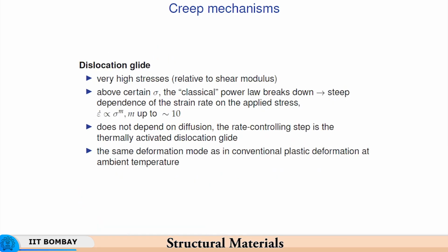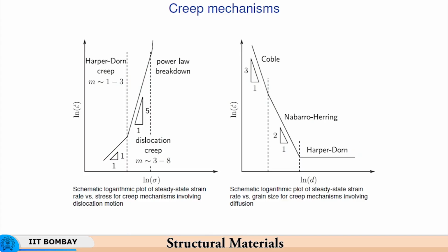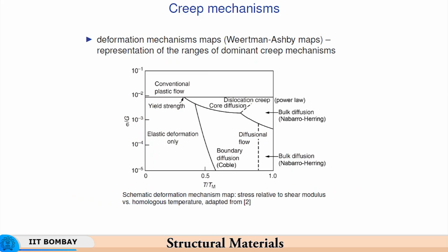So, we have seen that when different creep mechanisms operate, they operate in different domains of temperature and strain rate. They operate in the different ranges of temperature and time that is available, and therefore, we see that at relatively lower temperatures we have no creep at all. You have elastic deformation, then there is a permanent deformation even when you are below the yield strength. So, all these stresses are below the yield strength, and in spite of that you have significant diffusion and diffusion related plastic deformation which is called as creep.